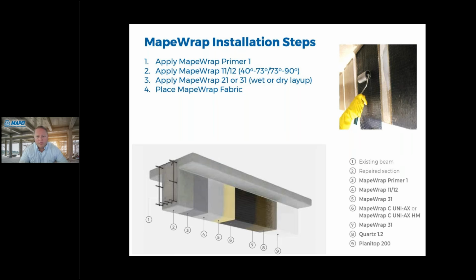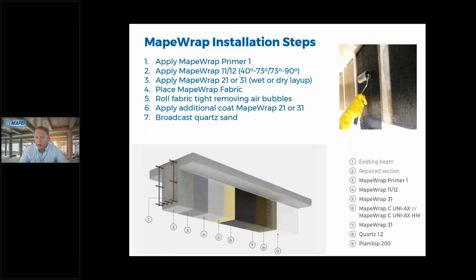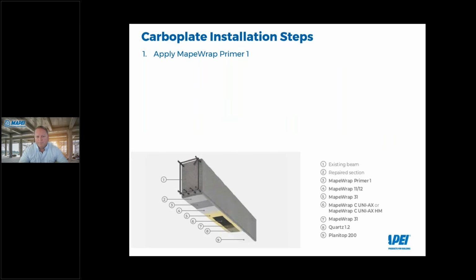So, place the fabric. Once you get it wet, you'll roll the fabric, removing air bubbles. It's like a ribbed roller. This is what the picture in the top right shows. And then you'll apply an additional coat of the 21 or 31. You'll broadcast some quartz sand, and then you can paint it or coat it. Typically, an acrylic paint coating is used over the system.